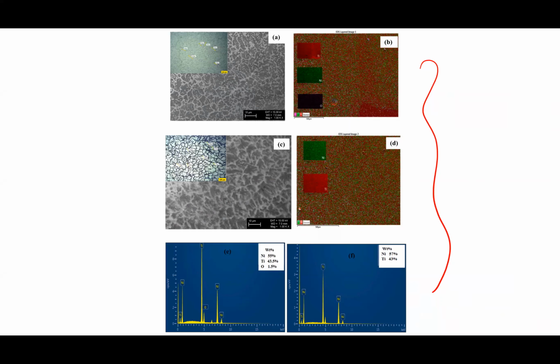Whereas in the case of B and D, we show some elemental mapping results in a WAAM deposited track without and with mark, and the different regions rich in titanium and nickel are located at different layers. So in samples without laser marking, oxide layers are formed due to a low cooling rate as compared to the marked sample, and the wide surface area in the laser marked samples leads to high heat flow to the substrate and the previous layer, leading to a higher cooling rate.